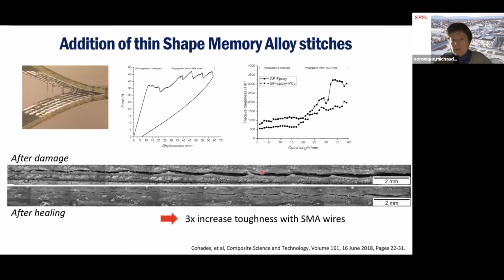We can show it here. This is a picture where you see the fibers being broken after we really opened the crack. But if we do DCB with a forced displacement, we see that in the zone where there were no SMA wires, we get the normal behavior that we had. But then at the zone where we started to have the SMA wires stitched, we had a big threefold increase of the fracture toughness due to the presence of the stitched SMA wires.